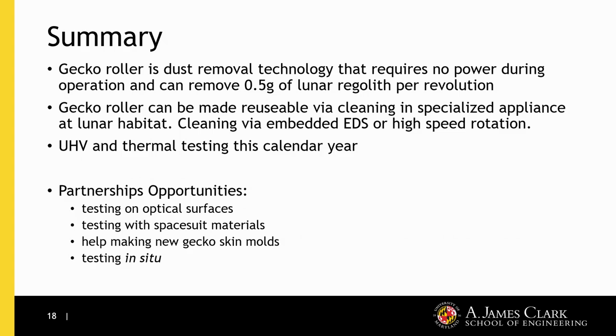So in summary, the gecko roller is a dust removal technology that requires no power to remove dust from a surface and can remove about 0.5 grams of lunar regolith per revolution of this roller. And to give you an idea of size, it's just the same size as your typical lint roller. And the roller can be made reusable via cleaning in a specialized appliance, either via EDS or high-speed rotation. And we're planning to do ultra-high vacuum and thermal testing this calendar year.